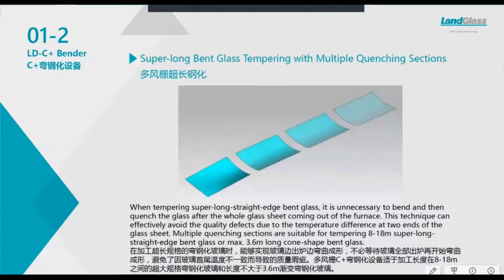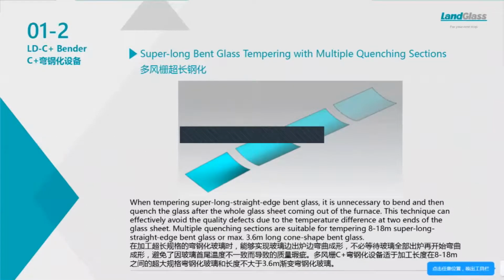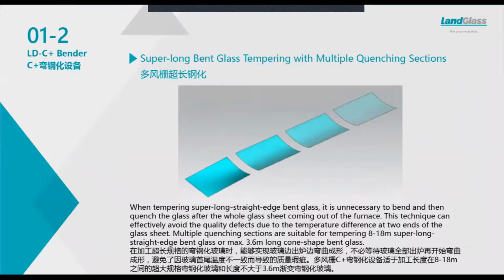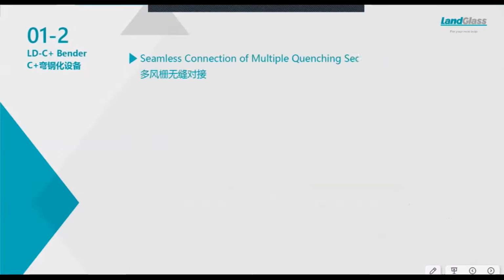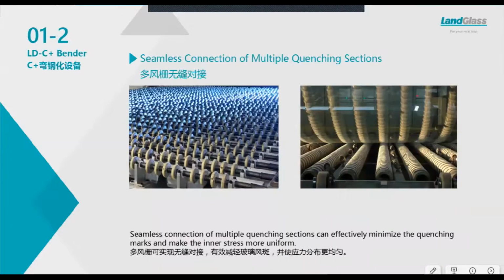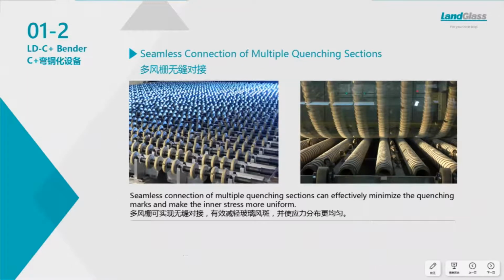When tempering super long straight edge bent glass, it is unnecessary to bend and then quench the glass after the whole sheet comes out of the furnace. This technique can effectively avoid quality defects due to the temperature difference at the two ends of the glass sheet. Multiple quenching sections are suitable for tempering 8 to 18 meter super long straight edge bent glass and maximum 3.6 meter long cone-shaped bent glass. Seamless connection of multiple quenching sections can effectively minimize the quenching marks and makes the inner stress more uniform.